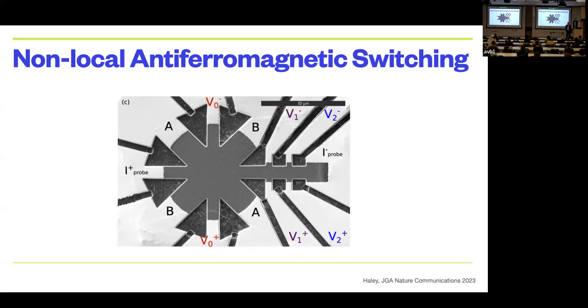So our collaborator, Jeff Neaton, did some pretty extensive density functional theory. I'm not sure if this is an explanation or just a statement, so forgive me if I haven't answered your question, but what they did is that they calculated the minimum energy for different magnetic orders. This is what the DFT folks can do. They can calculate stripy and they calculate zigzag. And what they found was that a next nearest neighbor interaction, depending on its value, could make the zigzag a lower energy than the stripy. In other words, the system would go zigzag because of that next nearest neighbor interaction.